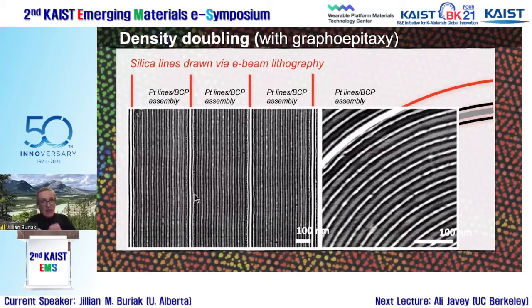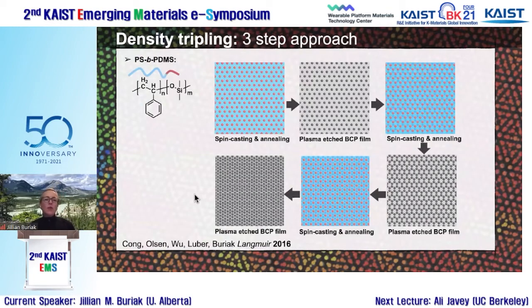And so Shin, the heavy weightlifter guy, said, all right, what if we can do density tripling, but I'm going to separate these 3 steps and increase the complexity of the processing, admittedly. Okay, so this is just fundamental science. But he did a spin casting and annealing of a block copolymer, polystyrene-block-PDMS, that gives you the dots. Plasma etches it, gives you the dots. So there we just have silica dots. And then he spin coated another layer of the same block copolymer. And so at this point, we had no idea whether the second block copolymer self-assembly process would register with the first one or whether we would get a mess.